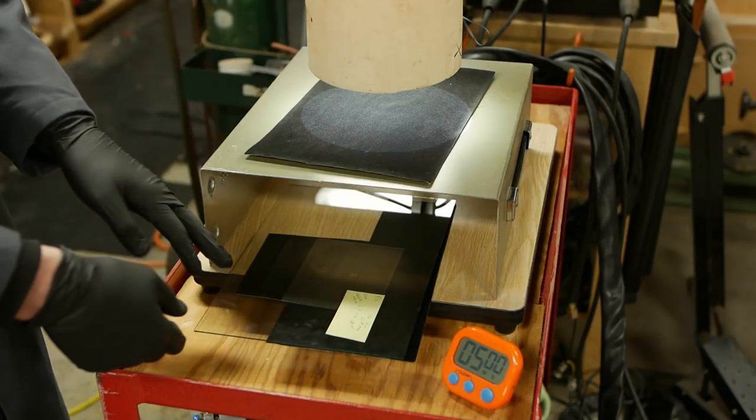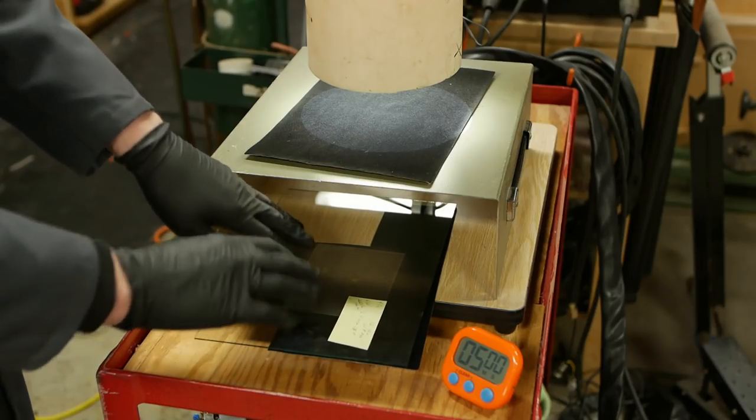And you can see in a previous run, even though this looks really primitive, and it is pretty primitive, it works well because you can actually see Newton's rings in there. So the glass really is compressing the film down to the slide below.